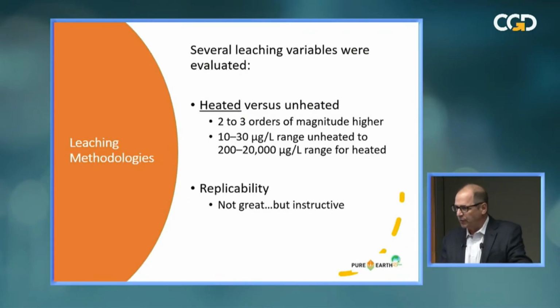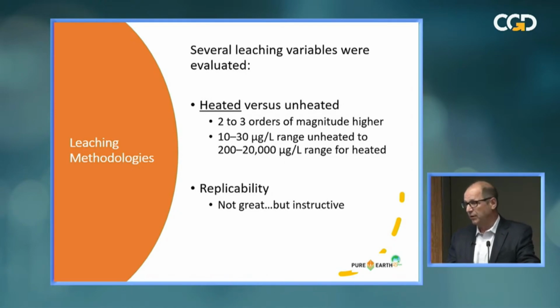So one of the questions we addressed, heated versus unheated. First we put 5% acetic acid in pots and let them sit there for not hours, but days. And then we also took a selected number of the pots and subjected them to heated leaching, where we boiled them for several hours, and again, measured lead concentrations in a time-stamped series throughout. And what we found was the heated leachate was 2 to 3 orders of magnitude higher than unheated room temperature leaching, even if it was left for days. And these are very high levels, of course, 10 being the drinking water standard, and finding levels of 200 to 20,000 is significantly above that.